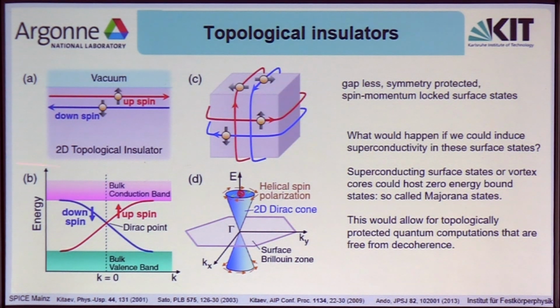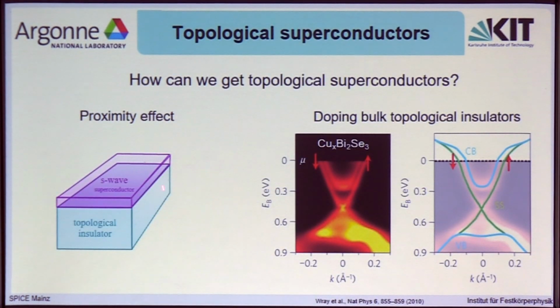Now, while those systems were discussed theoretically, only with the discovery of a real bulk topological insulator also came the realization of how to actually make a topological superconductor. And there are two possibilities to do that. One is by the proximity effect. We could deposit an s-wave superconductor on top of a topological insulator and thus induce superconductivity there. The other way is by doping the bulk of the topological insulator, thus making it superconducting, and have topological surface states here as well. So I'm going to talk about the second possibility, and the topological insulator of our choice will be bismuth selenide.